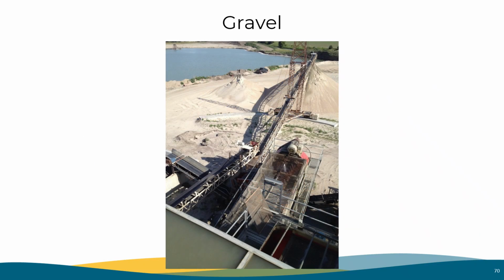So let's dig into some aggregate production. This is a photo of a gravel pumping operation at a wet pit in Nebraska. This is very typical along the rivers of Nebraska. In this process, equipment is used to dredge gravel and sand aggregates. The aggregates are screened to size, and the water is then pumped back into the pit. Large fragments are separated out, and the remaining aggregate is conveyed into stockpiles.